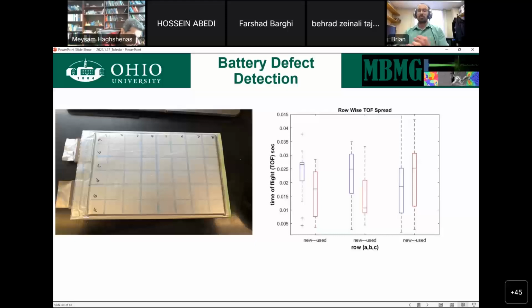We have a battery that we charged in negative 10 degrees Celsius, and one for this result that we charged in negative 20 degrees Celsius, trying to cause damage in the battery. We have since done one, I don't have the results on that yet, we're still processing them. We've since done one at negative 40 degrees Celsius to see really how bad that was, and we actually monitored the acoustic emission as the battery was charging, and we're able to see damage happening as we charge the battery.